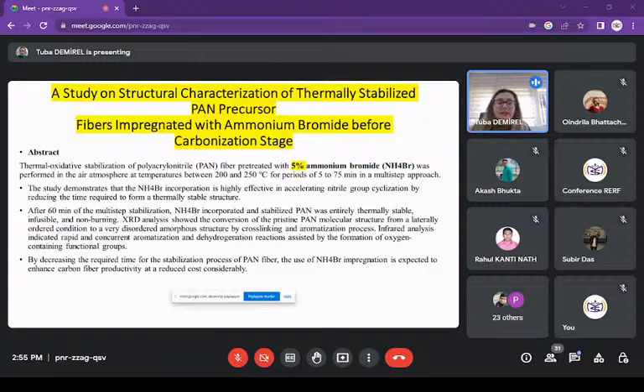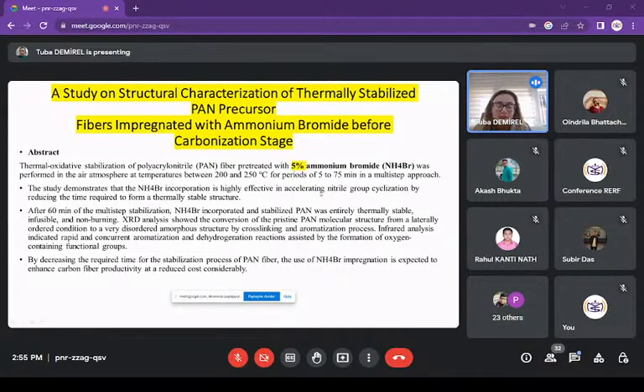The studies demonstrate that ammonium bromide incorporation is highly effective in accelerating nitrile group cyclization by reducing the time required for thermal stabilization. Structure is very important, and this ammonium bromide accelerates stabilization, so the PAN fiber is not flammable after 60 minutes, then the color has become black, a whole black fiber, decreasing the time required for the stabilization process of PAN fiber. The use of ammonium bromide impregnation is expected to enhance carbon fiber productivity and reduce cost considerably.